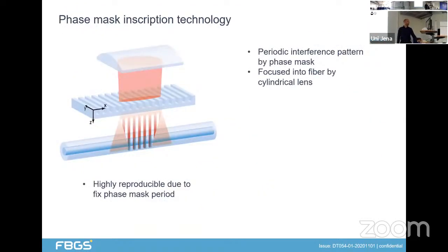The method how we do that is the phase mask technology. That means the grating period is generated by a phase mask where the broad laser beam is diffracted into the +1st and -1st diffraction order. And in the overlapping pattern, a periodic interference pattern is generated, which is then focused by a cylindrical lens into the core of the fiber. The advantage is that we use a phase mask made of fused silica, and the process itself is highly reproducible. So if you write the same grating several hundred times, we get the same period because this is defined by the phase mask.